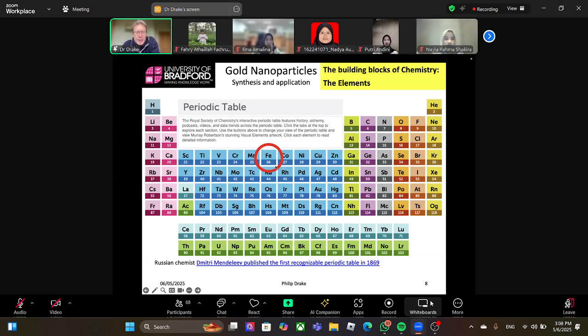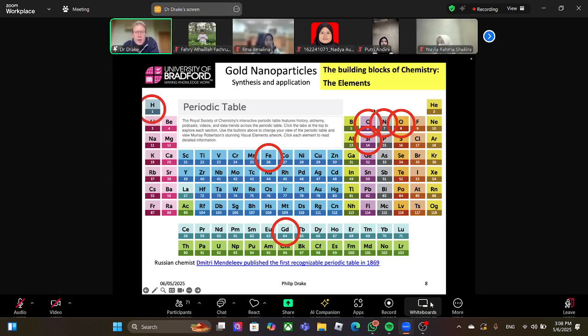I tend to use iron to make iron oxide nanoparticles. I use gadolinium. I dope the gadolinium into the iron oxide to make modified iron oxide particles. I use silica for glass coatings with oxygen. Silicon oxide is glass, so a lot of oxygen is in there. Carbon for the polymer coatings. There's always a lot of carbon involved. Carbon and hydrogen go hand in hand.